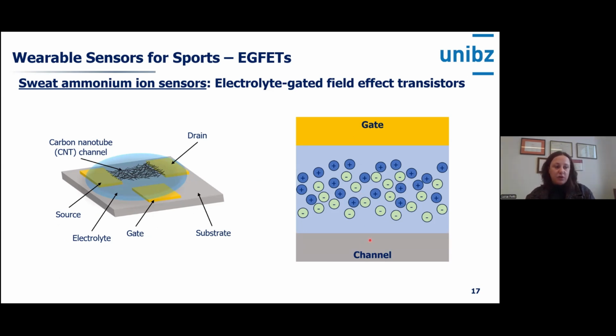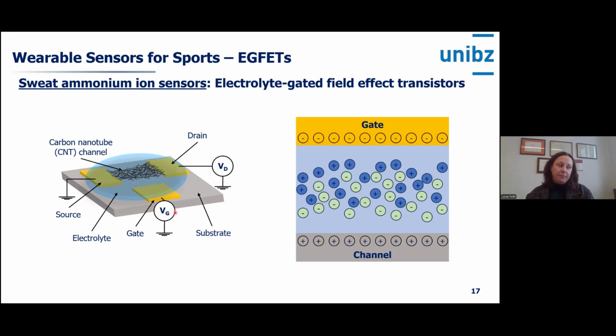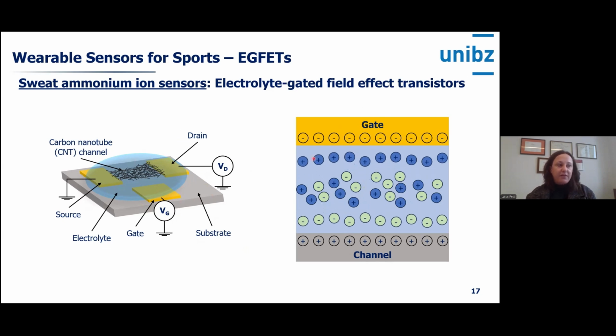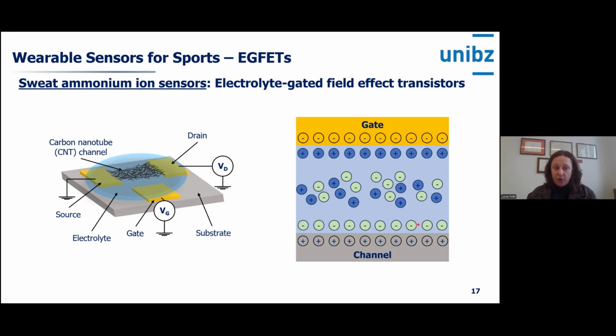This is how the device works, very briefly. What you see here is the cross section with the channel, the carbon nanotubes, the electrolyte with all the ions, positive and negative, and the gate. Even if it's a planar geometry, if we apply a voltage between the gate and the source, and between the drain and the source, with the source grounded, a negative voltage at the gate, because we are talking about a p-type semiconductor, what is happening is that with the negative gate we have a rearrangement of the ions. The positive ions get attracted to the negative gate, and the negative ions to the opposite side. And so we have a variation of the conductivity in the channel, which is what we then measure in the current.